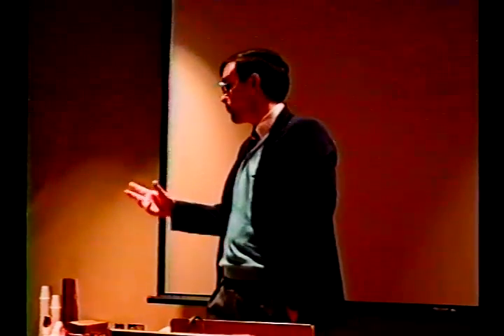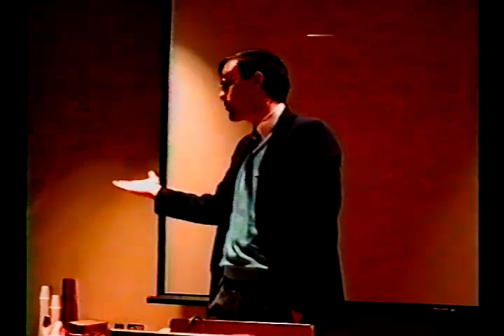We've tried to control the power rather than the time. The time is supposed to be consistent from run to run. But we haven't tried to vary that time and keep it in there for a very long time, because from our perspective, the reaction's over when you see this color change, and then you can do infrared to show that all the carbon monoxide's gone. That's a real good point. It's interesting. It'd be nice to do some of those kinds of experiments.